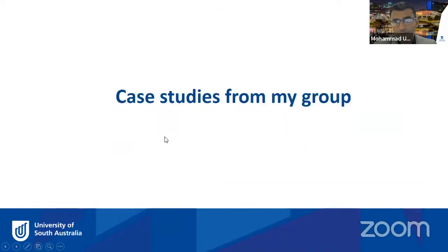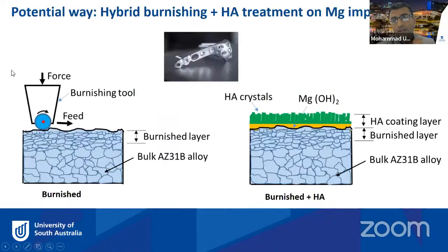So I'm going to give you a few case studies from my research group here. One example is that I mentioned about the implant. Generally, we thought we can apply the ball burnishing technique, which is basically nothing else: you apply force onto the material by a spherical ball or roller. So this ball applies compressive stress into the material, and then plastically deforms the peaks and valleys of the material. So you can improve the surface finish, and you also modify the grain of the material. Generally you may make the grain from coarse to fine to improve some of the surface properties.